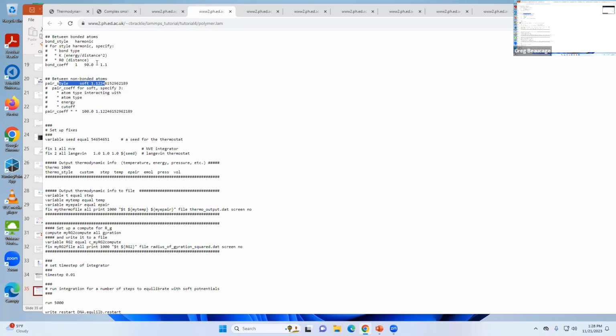It's written in the LAMMPS code to get things to straighten themselves out. Lennard-Jones would crash if they were on top of each other, I think. So the soft allows them to be on top of each other, and it'll still run and gently move them apart, so you don't have a hard crash. This is a way to get the system into a position where you could do the simulation on it. In the next part, it'll say pair style, it'll change it for the actual simulation, right?